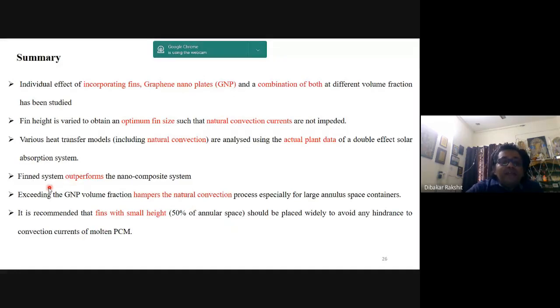So one important finding which we concluded from this is that the fin system, which is not having any GNP imbibed into the phase change material, performs better in contrast to the system where we are having the nanocomposite introduced in the phase change material. And then one more thing was that exceeding the GNP volume fraction will actually hamper the natural convection which is happening for the heat transfer during the charging and the discharging, which is also not very advisable to explore. So these are some of the things.